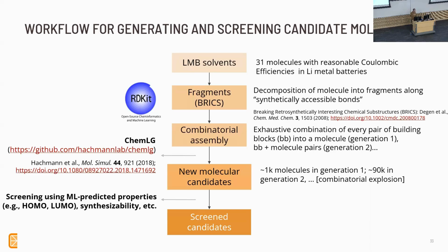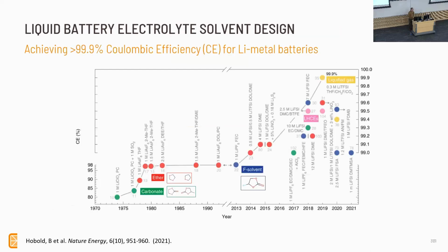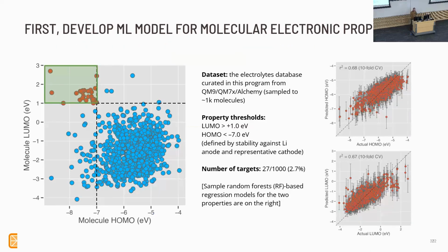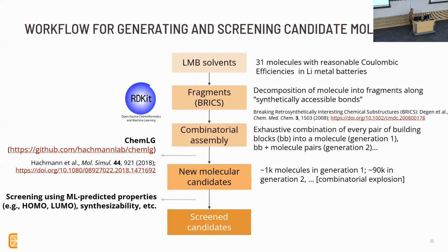So we went through, we made this large workflow here to try to find these lithium metal battery solvents. We basically took the good solvents in this first step. We found 31 that were known to be very good molecules, basically the stuff from this plot. We broke it down into their constituent subcomponents, fragments, we call them, and there's a method called BRICS for decomposing these molecules into these fragments. And then you take the fragments of the good molecules and you just recombine them like Legos into new molecules.